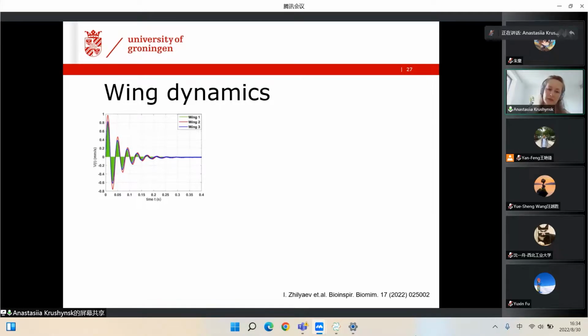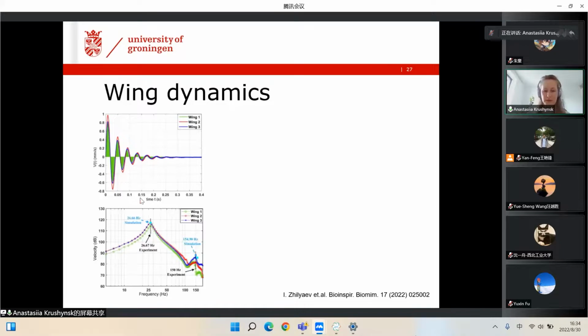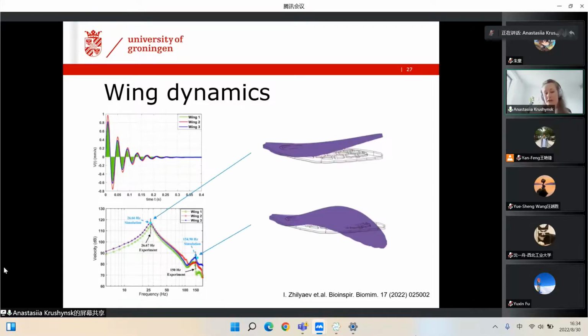And in the frequency domain, we were very happy to see that the first eigenfrequency of 3 different samples printed under different conditions, so under different orientation, is the same. And most importantly, it coincides with our finite element simulations almost perfectly, so the difference is negligible. And the agreement for the third mode is also quite good. So we were very happy with that, and then decided to check the next property.